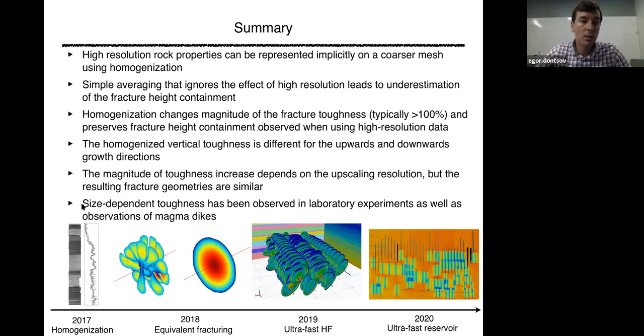And another thing, which again I don't want to open this kind of can of worms, but the results demonstrate that when you homogenize stress, this is size dependent, right? So it says that your effective fracture toughness is essentially size dependent, and it scales as a square root of the layer size, right? And this is something that has been observed in lab experiments and in field data for magma dikes. So there is a lot of discussion in the literature of whether the fracture toughness should scale with fracture size, and some models actually assume square root growth of fracture toughness with fracture size. And if you think about it, if you homogenize to a scale commensurate with fracture size, you'll get this square root behavior of fracture toughness.